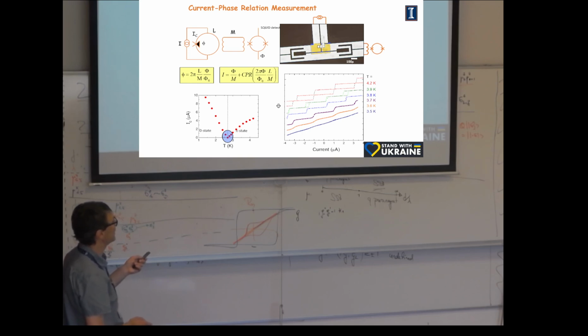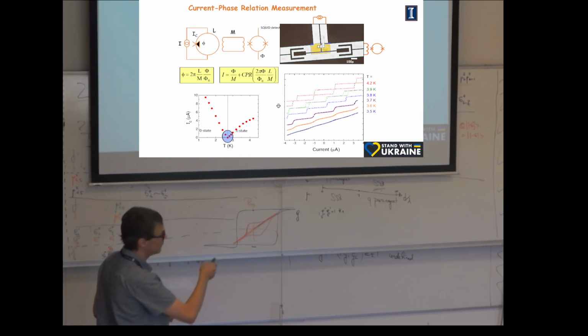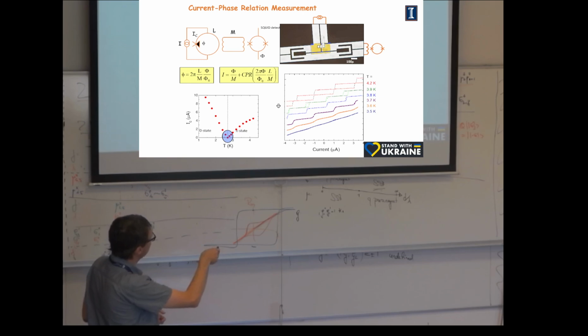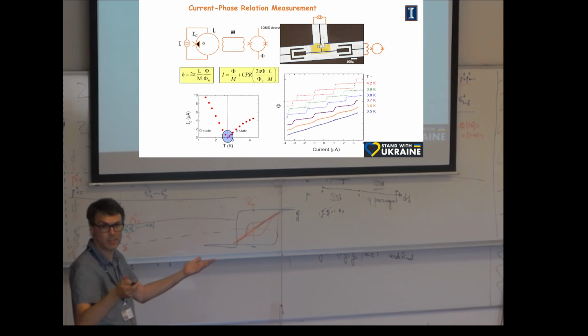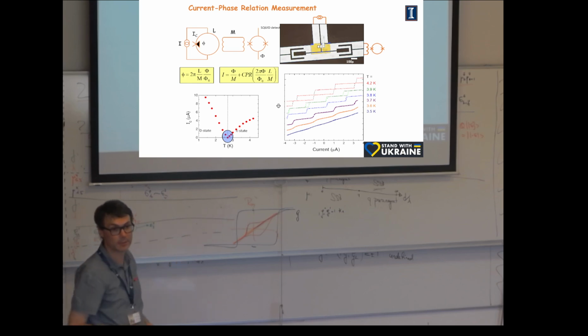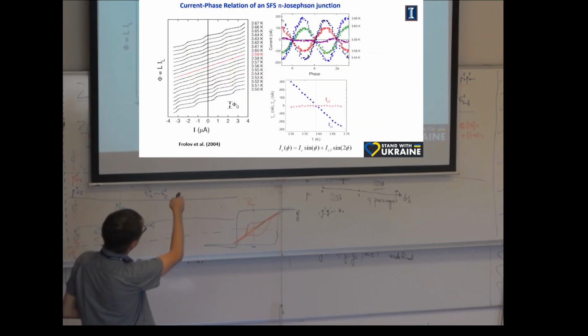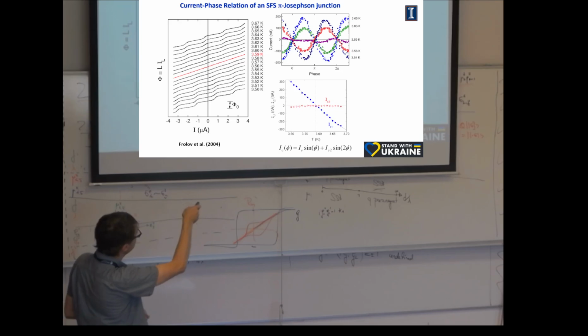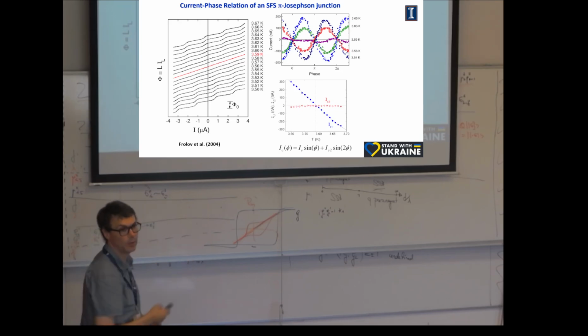Here, when the Josephson effect is too strong, it becomes hysteretic, multi-valued, but at lower strength you basically have an inductive, linear response: you put current here and it couples linearly to this flux. And on top of that, a modulation due to the Josephson effect, which is a wiggle. Then you do these wiggles from high temperature to low temperature, and at high temperature they are going like this, then it disappears, goes to nothing, and when it reappears, it's shifted. Here was near the cusp, and here is flat. And you can subtract the linear slope, and you see that you go from pi to zero,